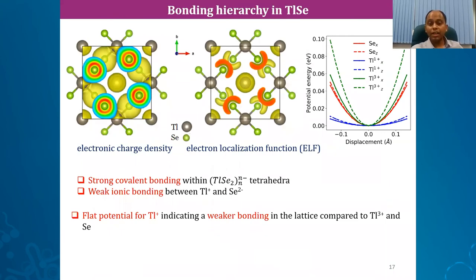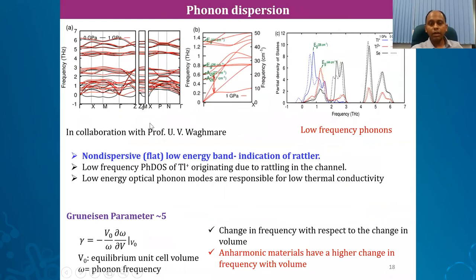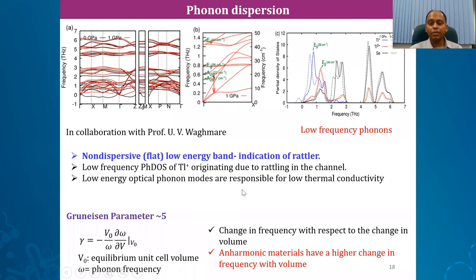To prove this experimentally, I first show the phonon calculation from my colleague Prof. Umesh Waghmare's group. It shows very low energy optical phonons and flat branches indicating rattling. These low-energy optical phonons are generated from the Tl⁺ atoms, as we expected from chemical intuition. We see that the three acoustic modes carry heat, but there is significant acoustic-optical mode coupling that scatters phonons and gives rise to the ultra-low thermal conductivity — purely from the perspective of bonding hierarchy and chemical bonding tuning.